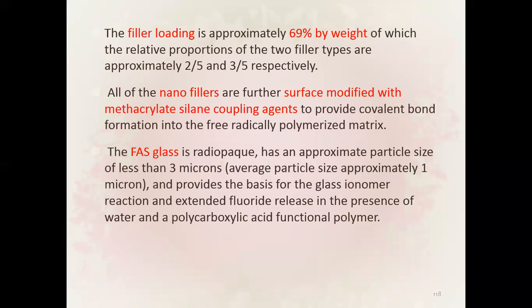The filler loading is approximately 69 percent by weight. The relative proportion of the two filler types is approximately 2/5 and 3/5 respectively. All nano fillers have surfaces modified with methacrylate silane coupling agents to provide covalent bond formation into the free radically polymerized matrix.